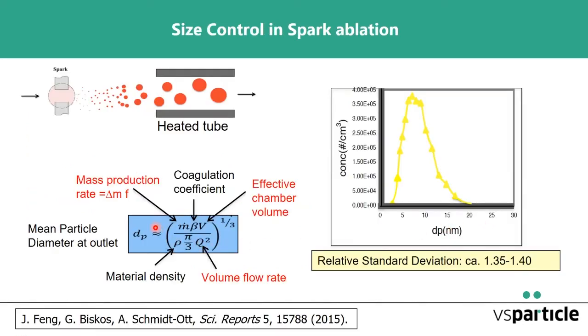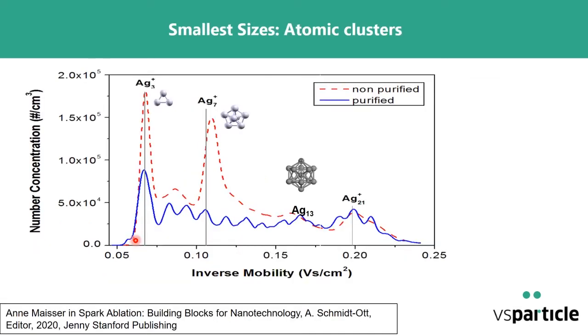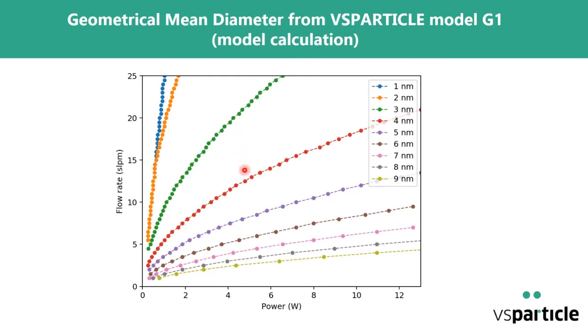If we look at this formula and adjust these parameters to make D very small, we can actually go down to the size of atomic clusters, and the smallest size is 1 atom. And actually this little shoulder here in this mobility distribution is due to silver 2, and then comes silver 3, which is somewhat more stable, and silver 7 is also nice and stable because it's such a nice geometric form, and so on. Right now there are not really any applications of these atomic clusters, but I think there's a great potential.